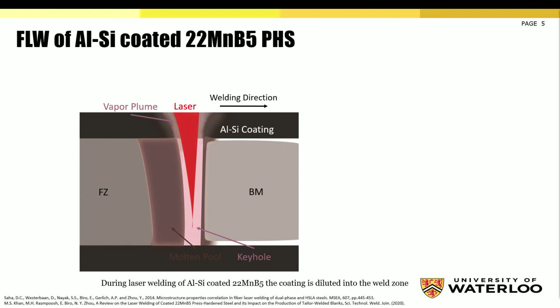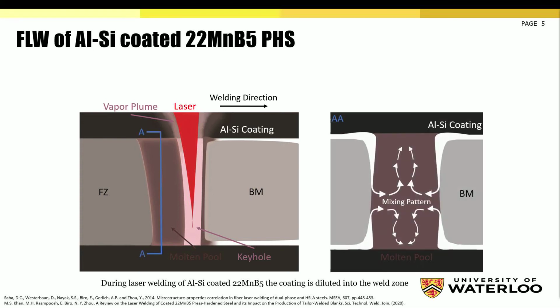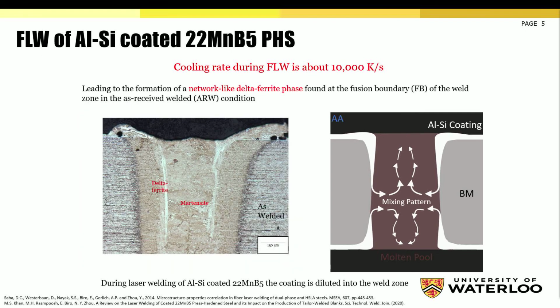However, during the laser welding of aluminum silicon coated 22 Mn B5, the coating is diluted in the weld zone according to the Marangoni convection flow, as can be seen by the cross-section AA. As the molten coating flows into the weld, the extremely high cooling rate during laser welding causes the aluminum to become entrapped along the fusion boundary as the weld pool quickly solidifies. This leads to the formation of a dual-phase microstructure in the weld, with a network-like delta ferrite phase embedded in a martensitic matrix.